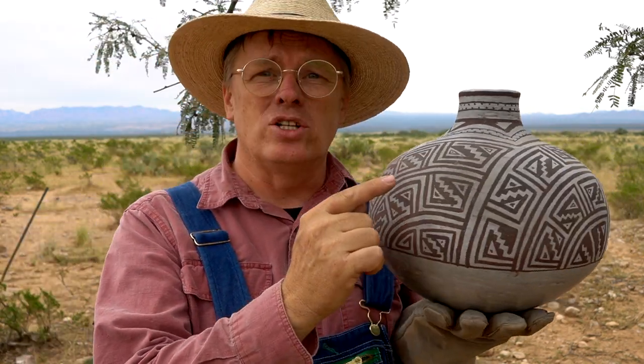Because this red will oxidize at pretty low temperatures. I'm thinking if you had a big galvanized tub or something that you could just shove over the top of the whole firing when it was done, that would dissipate heat faster and might allow you to go home sooner — obviously not authentic, but it might be one way to do this. I'm not completely dissatisfied with the results, but it's not as black as I'd like. Before I started smothering it, it was just as black as can be, and I took pictures with my phone to prove it. The white also isn't as good as I'd like — it's quite dark, it's got carbon in it. I think that had to do with the pit environment, maybe not enough air circulation or not getting temperatures up long enough to burn that carbon out. Tony Soares texted me with some real good ideas on this just a couple days ago.